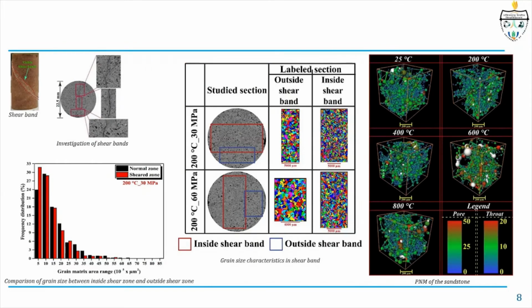After the triaxial mechanical test, the failed samples were used to investigate the shear band characteristics at different temperatures and pressures using the Australian synchrotron facility present in Melbourne. Here, inside and outside shear zones are taken for consideration and analyzed for their grain size variation and porosity. The microstructural observations of the sandstone was performed using the computer tomography based concept of digital petrophysics that enable visualizing and quantifying the pore volume, microstructure, and pore network models of sandstone with varying temperatures and loading stress.